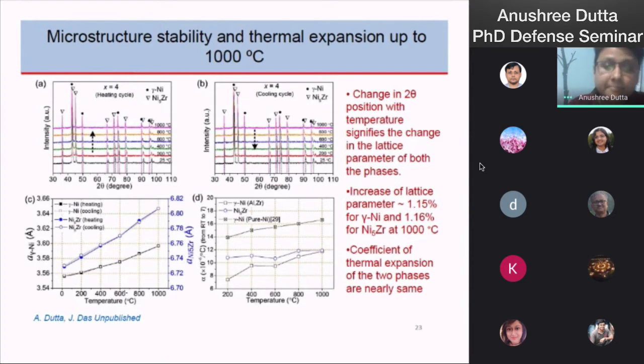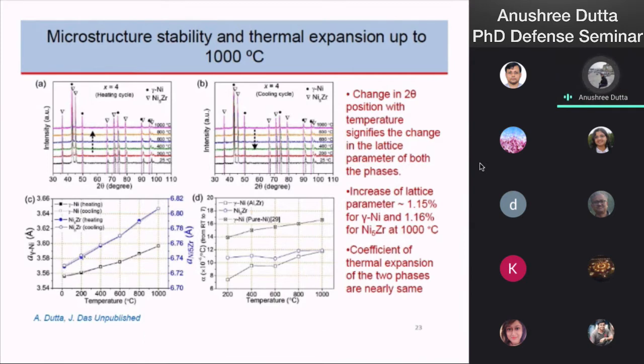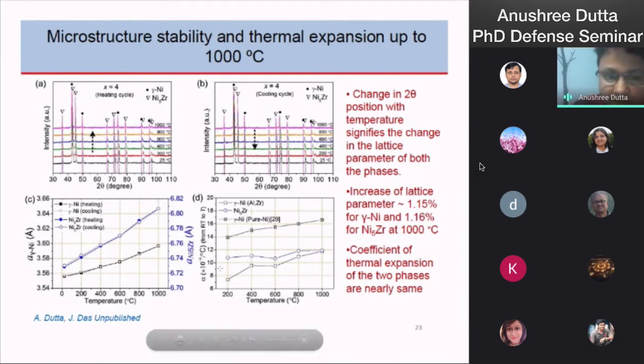Now, the lattice parameter, which I have estimated from Rietveld refinement analysis, is observed to increase with temperature linearly for both the phases, gamma nickel and Ni2Zr phases. The linear coefficient of thermal expansion as estimated from the increase of lattice parameter is plotted here with temperature. So we can find that both the gamma nickel and Ni2Zr phases exhibit nearly the same linear thermal expansion, which shows their high thermal stability at high temperature, which is actually beneficial for alloy to be used at high temperature. And the linear thermal expansion is lower compared to the pure gamma nickel.